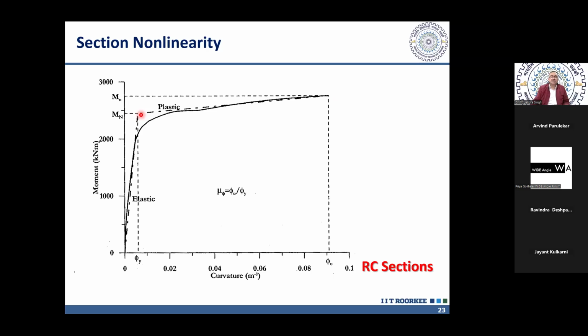So depending on the type of the section or reinforcement detailing of the section, this line may have a slight positive slope, it may be perfectly flat, or it may sometimes even have a negative slope. When it is perfectly flat, we call it plastic, or ideally plastic. This is strain hardening, and then there can be strain softening as well when it is sloping downward, with a negative slope. And the ratio of phi u to phi y is important. We call this curvature ductility, mu phi, that is phi u over phi y.